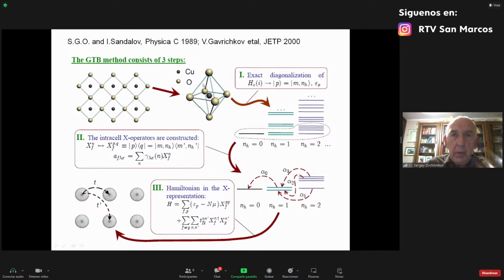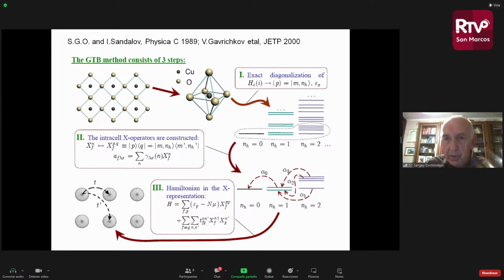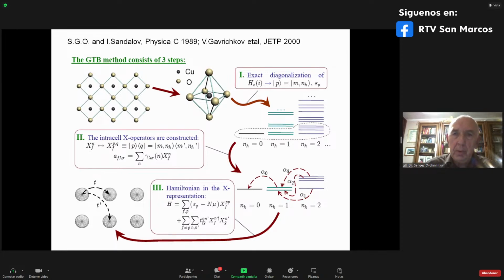When we have done this exact diagonalization, we obtain a set of different multi-electron states. For example, the vacuum state shown here with zero holes. This is the state corresponding to the d10 p6 configuration, so no holes on oxygen, no holes on copper. The next states are single hole states. It is a mixture of a hole on oxygen and a hole on copper, like for undoped La2CuO4.